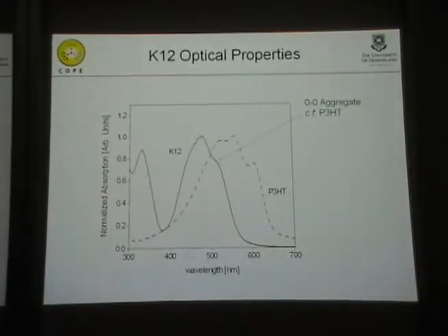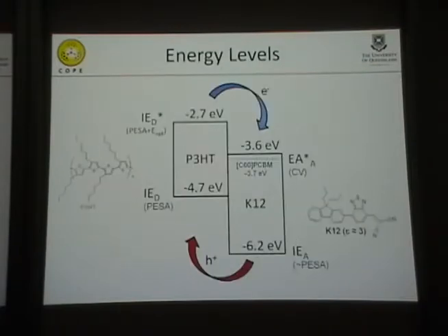So the optical properties: we see that there's some complementarity to the P3HT absorption spectra, and it also shares quite a strong 0-0 vibronic band absorption edge compared with P3HT. So this is an indication of strong intermolecular interaction.